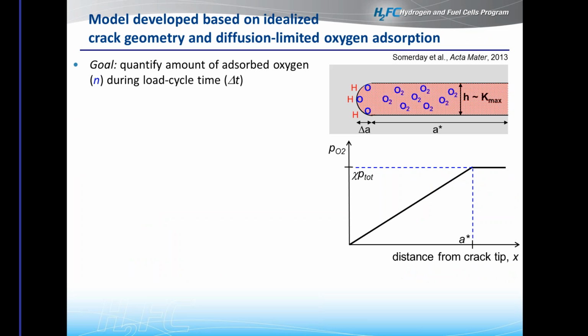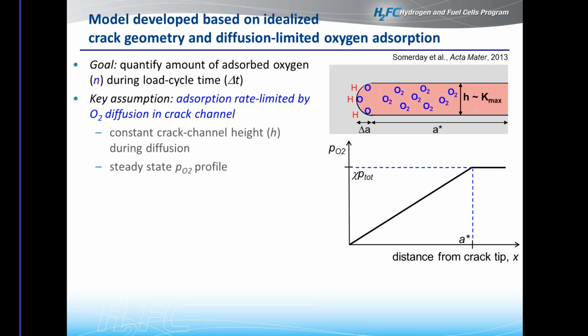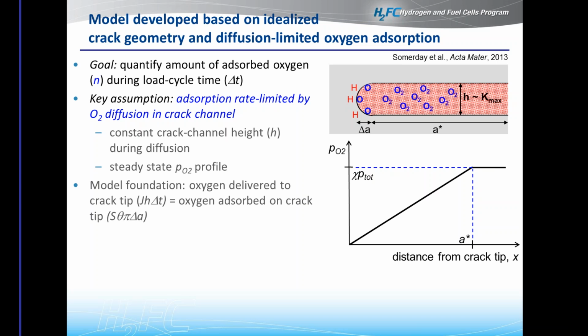So part of the model hinges on modeling, first of all, what the crack profile looks like, or the crack tip area. But the other part, the key assumption really, is that it's rate limited by the amount of oxygen that can diffuse down the crack channel and adsorb onto the surface. So in that, we used a steady state profile of oxygen, and we assume that the partial pressure of oxygen is consistent back in the bulk of the gas, but then it has a linear trend down to the crack tip. And then really it's just about modeling whether the oxygen delivered to the crack tip is able to be absorbed within a load cycle. So you can imagine the frequency that you're testing this at affects how much oxygen is able to travel down there, how fast it's able to travel down there. And also the R ratio dictates what the crack profile will look like. In other words, is there a pulsing effect of gas species?